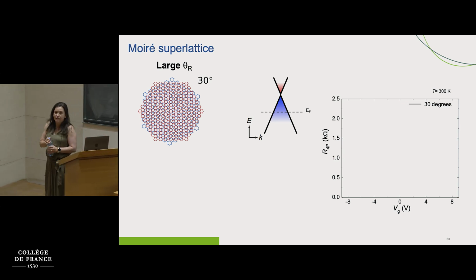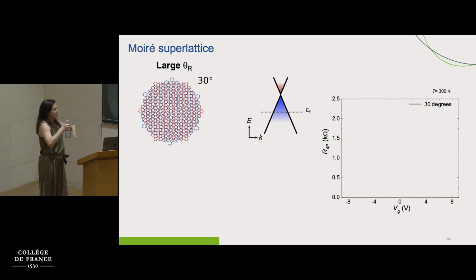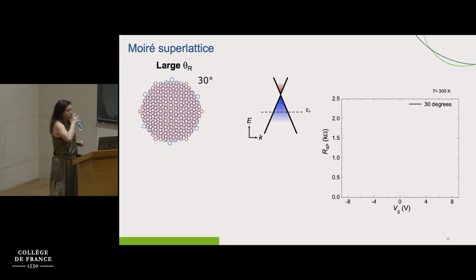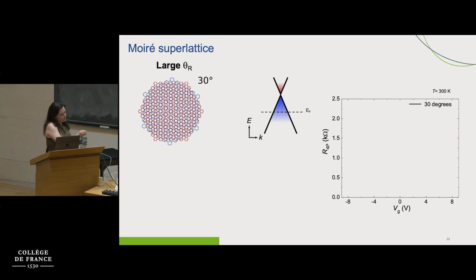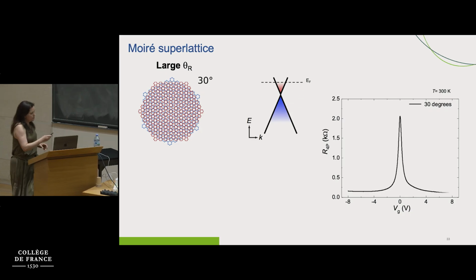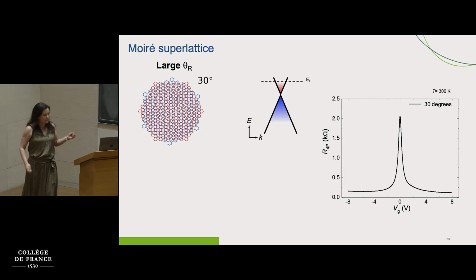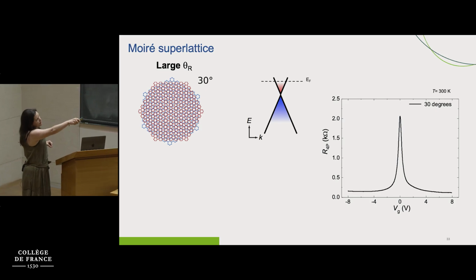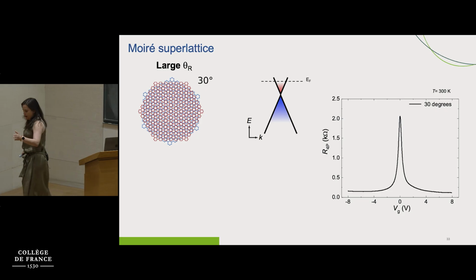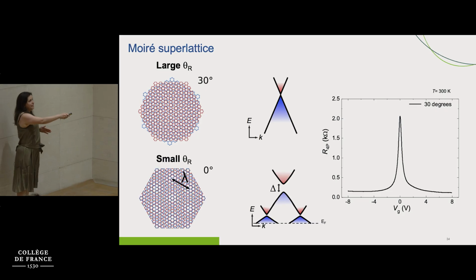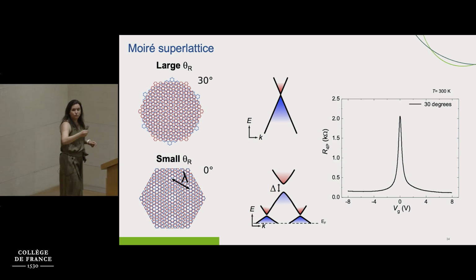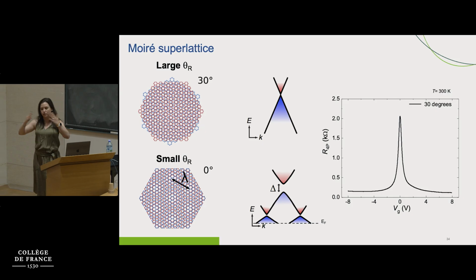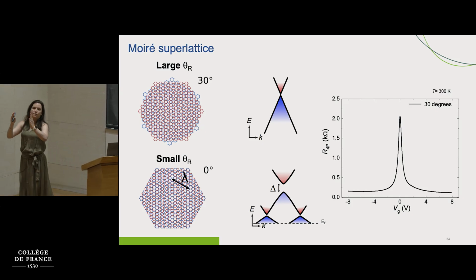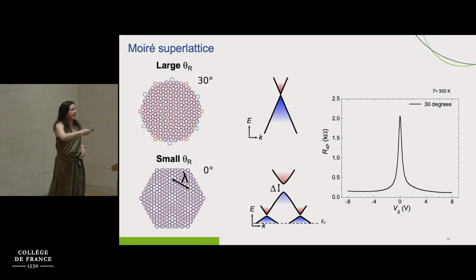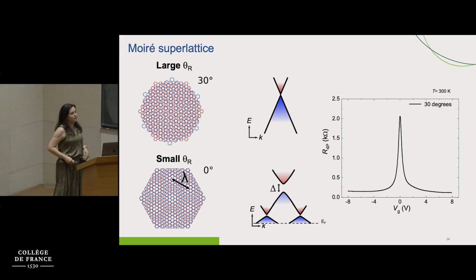If I have graphene on boron nitride, as I started saying, I have a linear energy dispersion. As in my previous example, if I measure the longitudinal resistance of my graphene flake, I just have a strong peak in the resistance. Now, if I align graphene and boron nitride, I have a superlattice of size lambda, and I'm going to modify the electronic band structure, and this is just band folding. Now I have a periodic potential that is superimposed, so my Brillouin zone is going to be smaller, my bands are going to be folded, and I'm going to have new energy gaps that appear in the system.